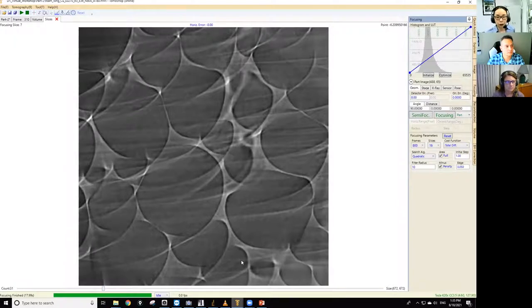You might see the sample movement effect, as you're seeing here, as streaking lines, either horizontal or vertical lines if you do a 0 to 180 degree scan. If you do a 0 to 360 degree scan, you probably don't see those streaks in one direction, but if you scan, let's say, a cylinder, you will see the cylinder cross section and you see another one bigger. When you have that doubled image, that's another sign that your sample was moving. So you probably want to be looking for signs of sample movement if you know that the sample is not too rigid and it might have moved during the scan.